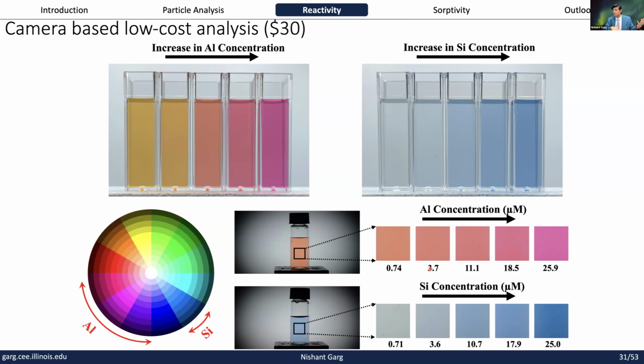And you can use as your ground truth ICP or UV-Vis, whichever is already verified, and then this camera method can work. One thing you should be very careful about is your lighting condition, your camera itself, all of these things, because if you're not careful, this can be sensitive and your numbers can change. I would recommend a consistent lighting condition and having the same camera to do this.